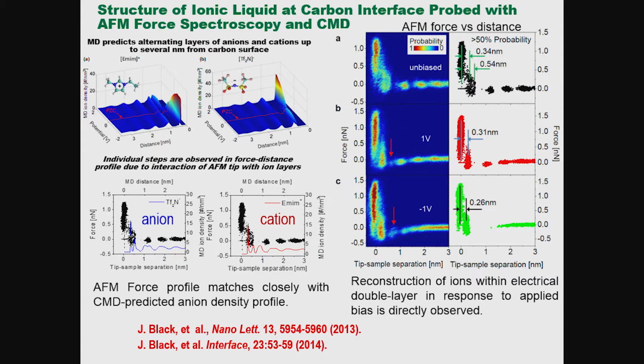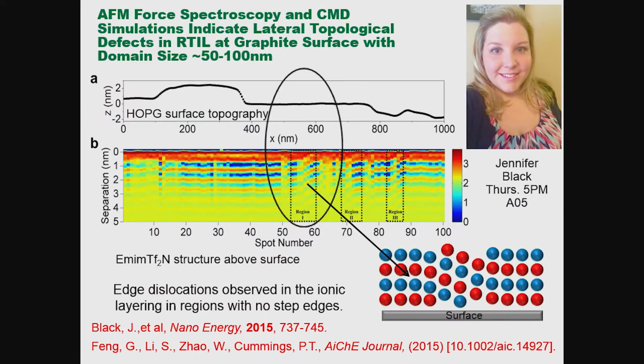This is MD simulations at open circuit potential, where you see that it's really the anion layers that are giving rise to this signal, which is something we don't quite understand yet, but apparently the anion layers are stiffer than the cation layers for this particular electrolyte. So that's something of great current interest.